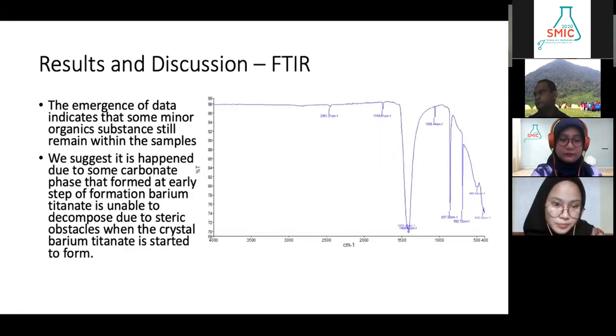The emergence of this data indicates that some minor organic substance still remains within the sample, which suggests it happened due to some carbonate phase that formed at an early step of the formation of barium titanate being unable to decompose due to steric obstacle when the crystal barium titanate started to form.